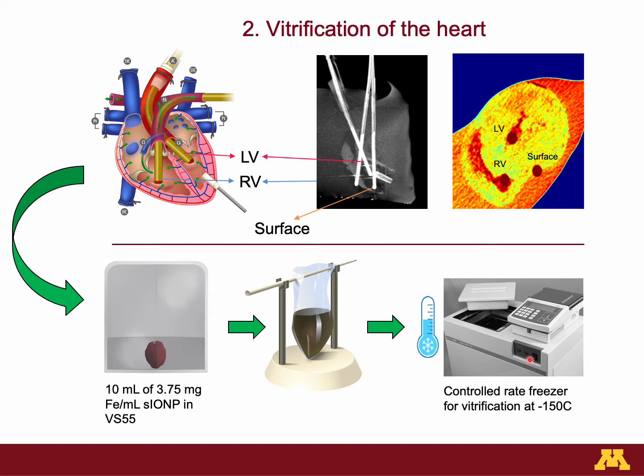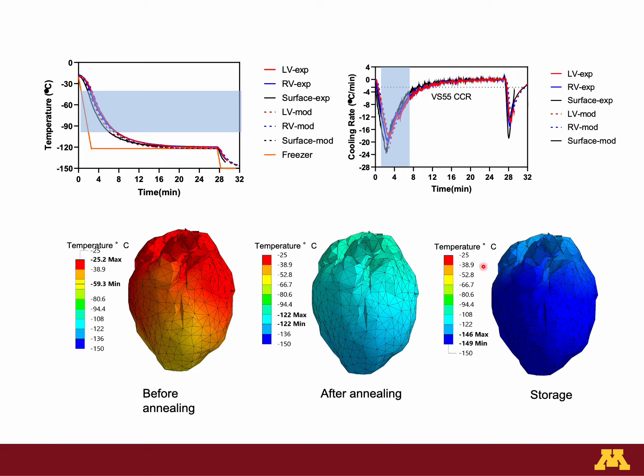The heart was placed in a controlled rate freezer, cooling at minus 40 degrees Celsius per minute to minus 150 degrees Celsius. During the cooling, we added a 25 minute annealing step at 1 degree Celsius above the VS55 glass transition temperature in order to reduce mechanical stress built up prior to entry into the glassy state. The blue region indicates the temperature region of particular danger from ice growth.